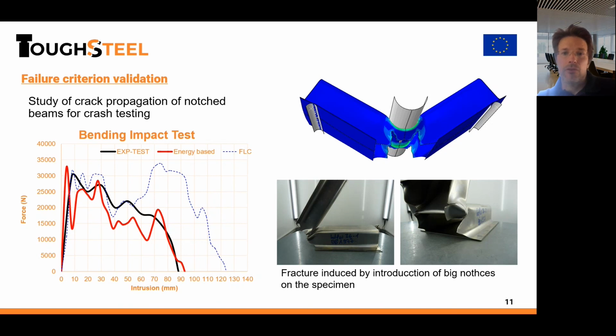And we are also working on the evaluation of the strain rate sensitivity, but in many analyses, the characterization through the slow rate is enough to analyze the failure in this crack condition. But in crash simulation, we need to take care when using the model because in some cases the strain rate is necessary to achieve good results.